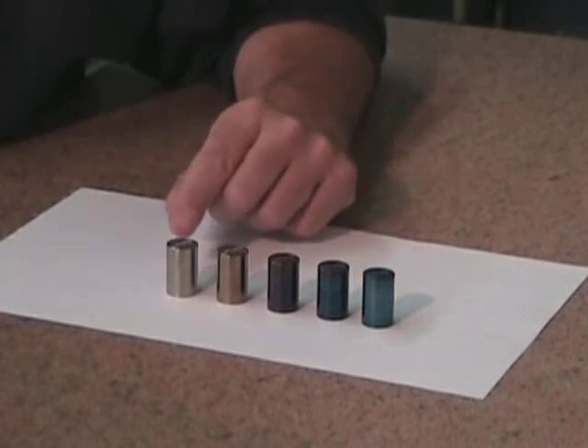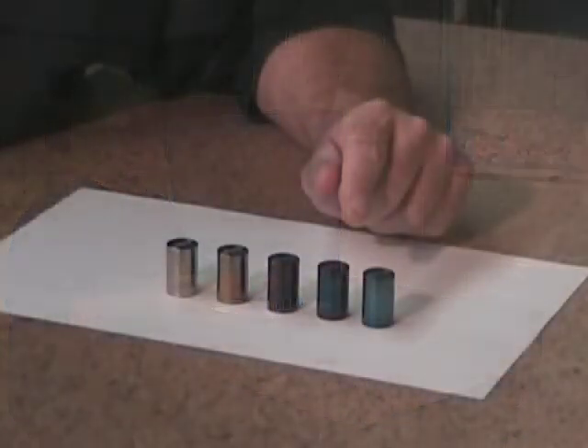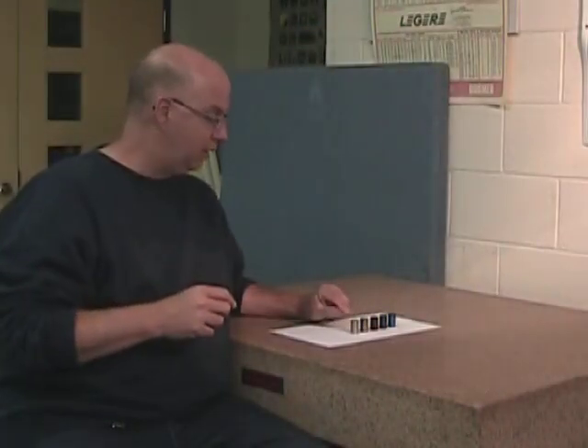Now that toughness comes at a price. Every time you increase the temperature, you decrease the part's hardness by a little bit. At 450 degrees, the hardness of the part is probably not affected. However, at 620 degrees, you're approaching what we call the full temper, and you're going to lose about 30% of your hardness. So it's a give and take. The main thing that we notice is that the colors are closely tied to specific temperatures. Now this is true for most steels.